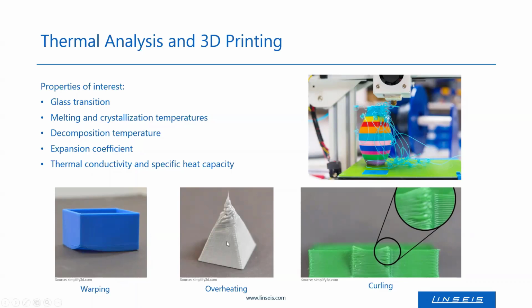A further problem can be overheating. So if the temperature management is not good, if the filament is heated too much, it can cause some touch effects, or further temperature issues can lead to curling, so that here the edges on the top bend a bit. So this is also due to some temperature gradients over the sample, and then forces move the edges to the top. So the most important properties which need to be known of the filament are the glass transition, the melting and the crystallization temperatures, the decomposition temperature, the expansion coefficient, and for the printed materials, it is good to know the thermal conductivity and the specific heat capacity.